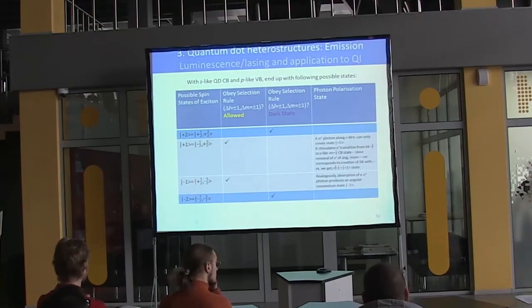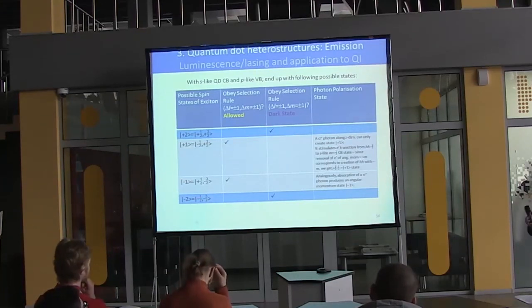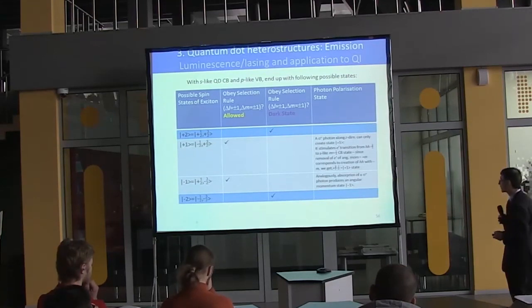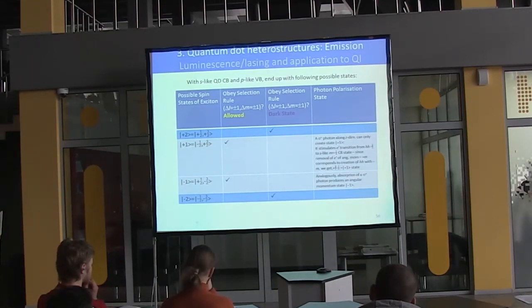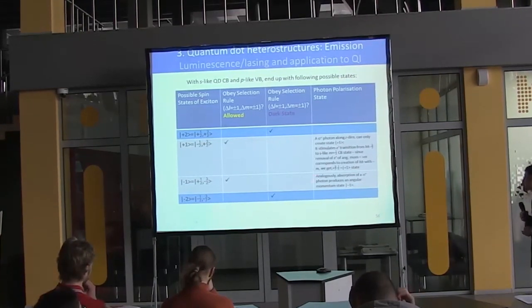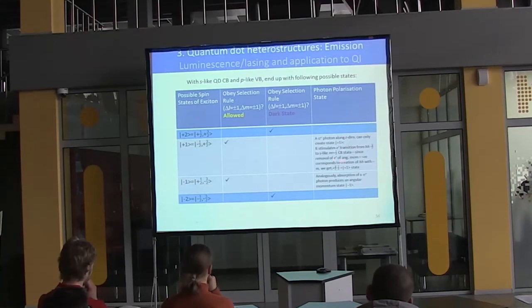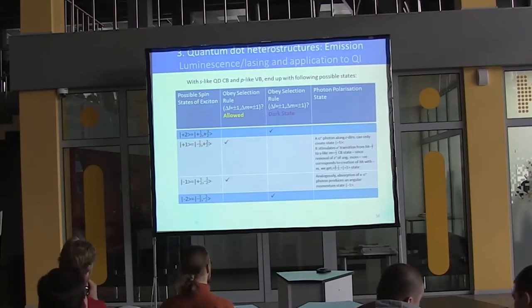So what does it tell me? What should I do in order to look at these two states? So if I took, and this goes back to the polarization thing I told you earlier, a right circularly polarized photon coming at this in the z direction, which means down onto the quantum dot, which is beneath me, it can only create the +1 state. Why? Because what it does is it's stimulating the transition from the heavy hole, the -3/2 state, to the -1/2 state. That's what it says over here. And why do I call that +1? Well, because the removal of the electron, which has angular momentum +1/2, in this case is going to be the -1/2, so minus becomes a plus, will correspond to the creation of a heavy hole with the minus state of angular momentum. So we end up with basically 3/2 minus the -3/2, if you like, or minus -1/2, which is equal to the +1.